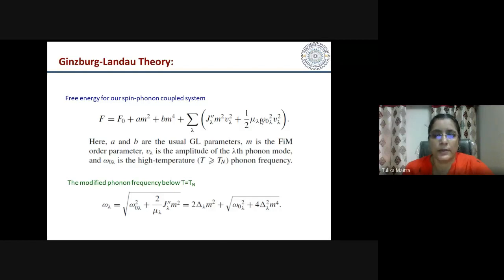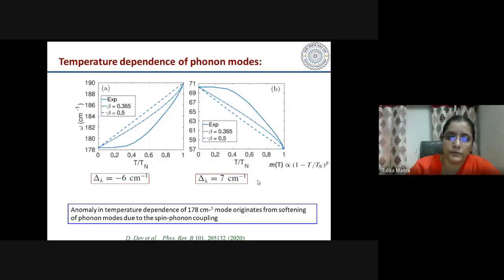When the magnetic order sets in at low temperature, then we have this term in addition to these terms. Okay. So the new frequency can be calculated due to the magnetic ordering. The new frequency can be written down in terms of this delta lambda, which we can calculate from DFT. Okay, so here we can calculate from DFT this delta lambda, and M, the temperature dependence of the magnetic order parameter, can be taken from experiment as well as from some models.